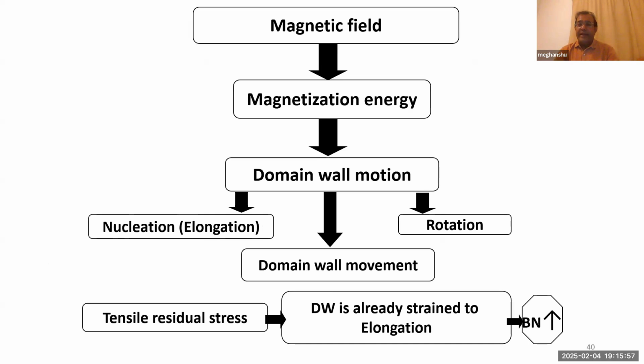Now, suppose the component has undergone a grinding operation. We have seen that grinding will induce tensile residual stress. This component has a grinding operation over it, and this grinding operation will induce tensile residual stress. It means it will elongate everything. It will elongate the void that we have seen in the schematic diagram. This tensile residual stress will elongate porosity and cracks, as well as the magnetic domain wall.